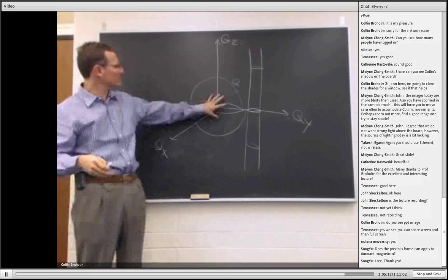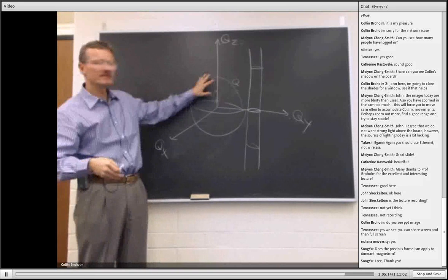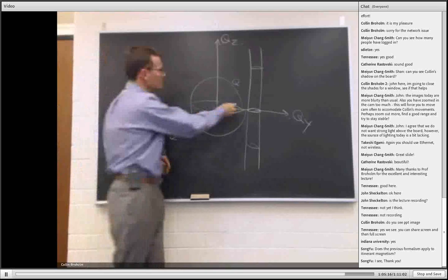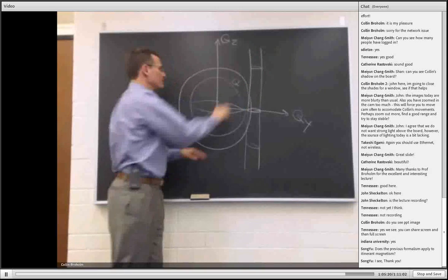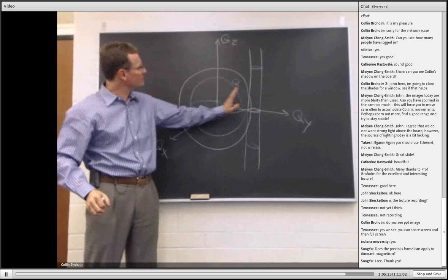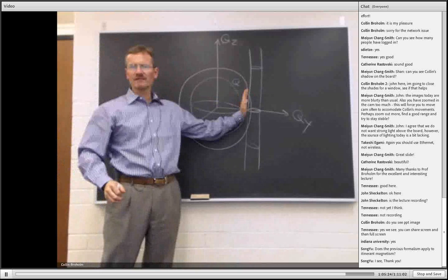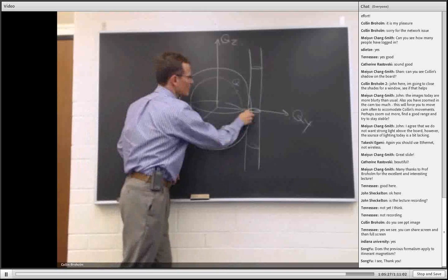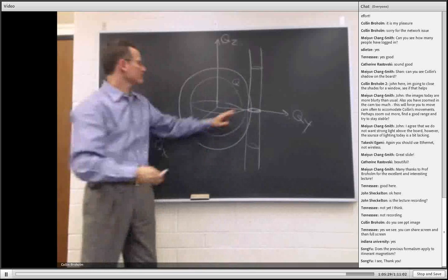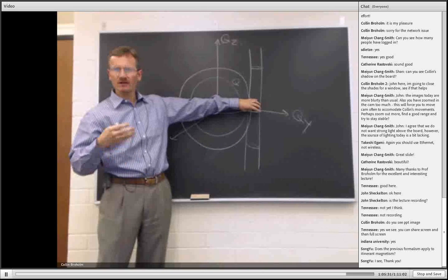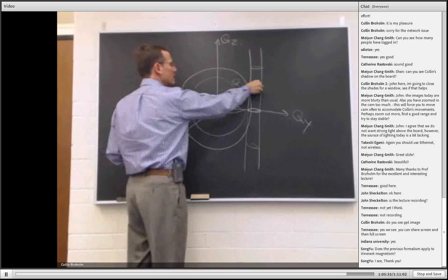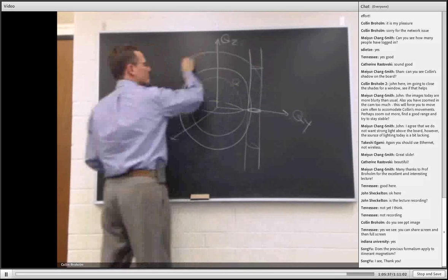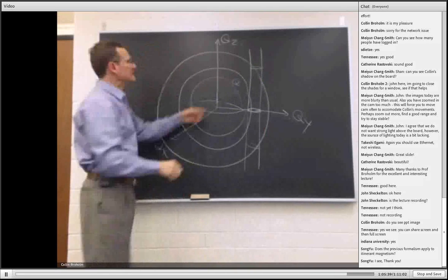At small momentum transfer, this sphere does not intersect any of these rods. But then there'll be a certain critical momentum transfer where I just begin to hit this rod. And that is where I'm going to see the very sharp feature, the sharp feature being the small extent of the rod in the plane of the two-dimensional magnet. And then when I go beyond that to larger momentum transfer, I'll be cutting through this rod.